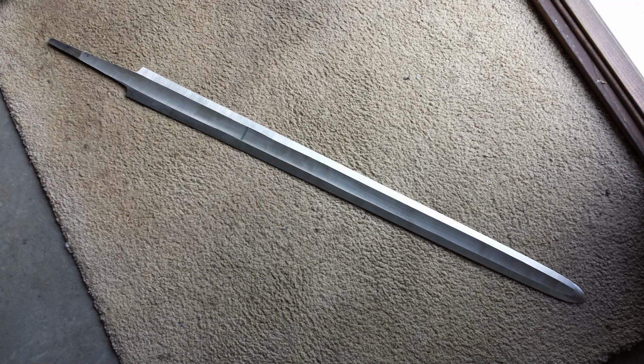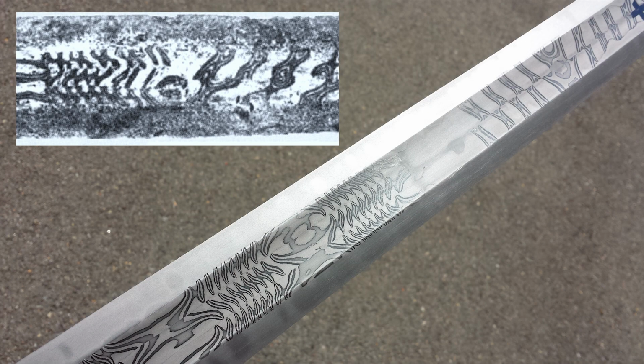Here's the final grind before heat treat and hardening the edges. After some more grinding, the weight wasn't too far off, but still too heavy. Unfortunately, not only the weight was off, many other things were wrong. For example, notice the transition between patterns here.